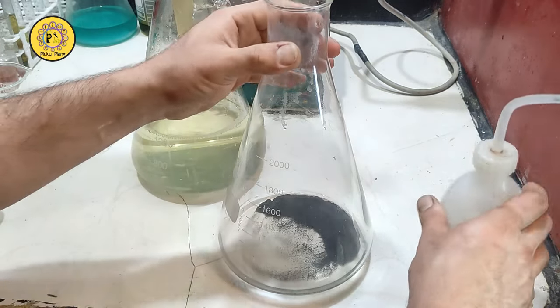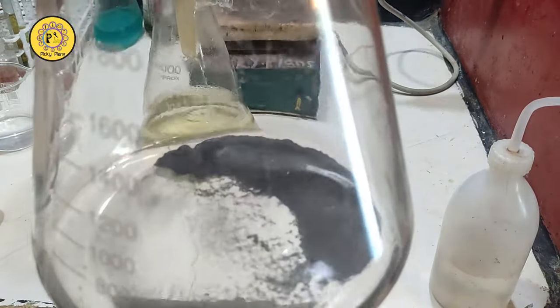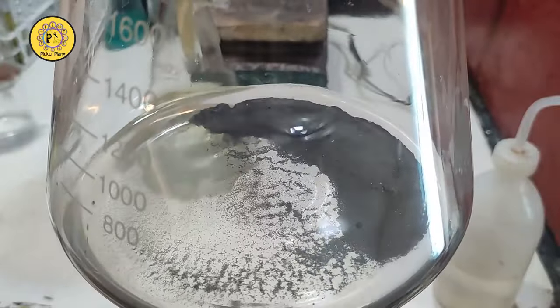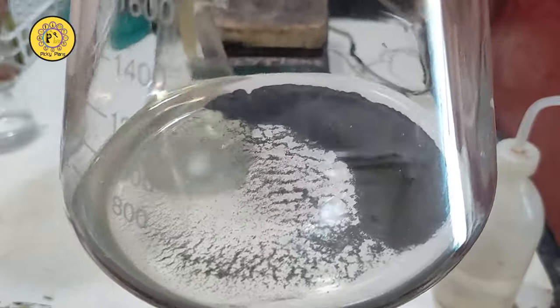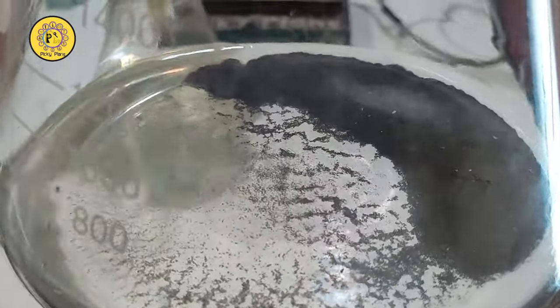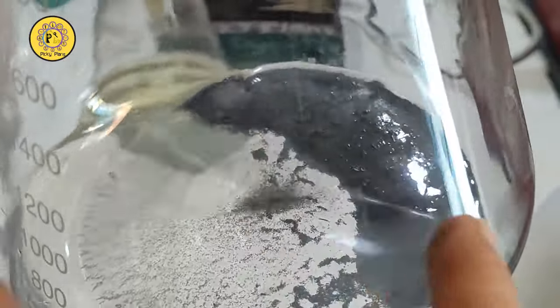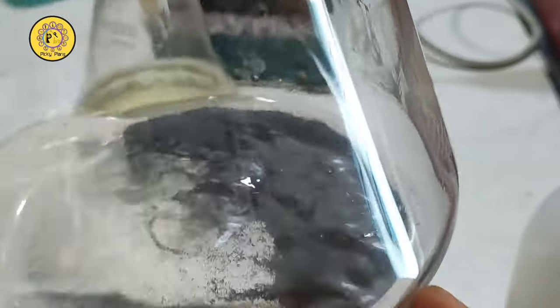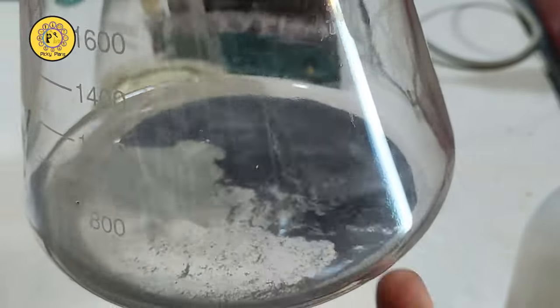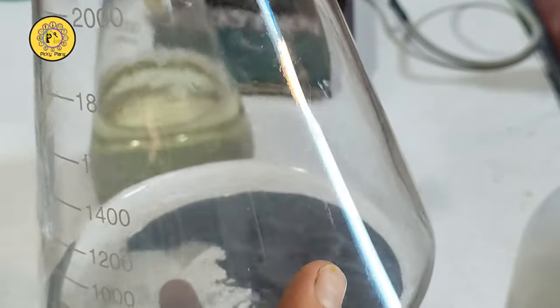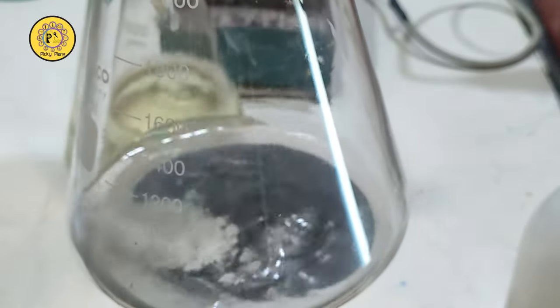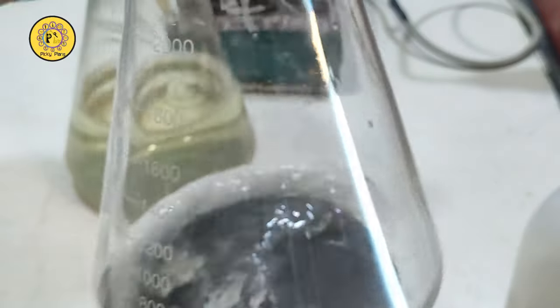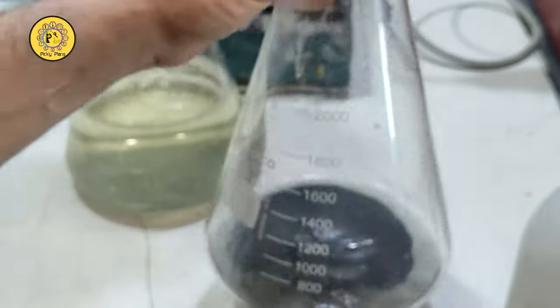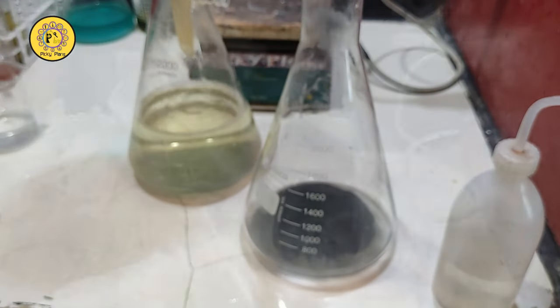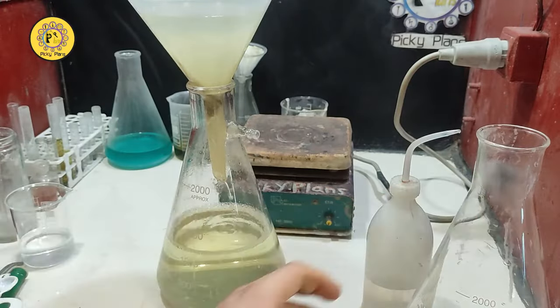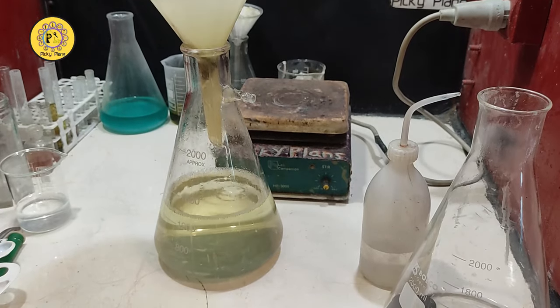Alright, zinc powder definitely carries gold on it. This is obvious with the floating form of zinc and some pores in the zinc powder. Actually, the zinc volume has increased compared to the first volume of zinc I added. Let's transfer this to a beaker before pouring off the excess water.